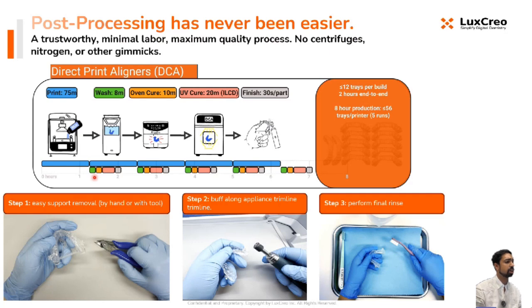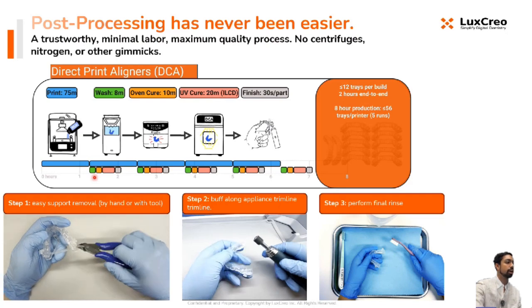Once your print is done, you remove the parts from the printer and put them in the wash box. You press either the powerful button or the aligner button, depending on the version of the wash box. Then you just press go, and it takes about 8 minutes, and it'll automatically and completely clean your parts with a guaranteed cleaning. You don't have to worry about using a centrifuge or anything like that. No gimmicks that can lead to less safe devices.